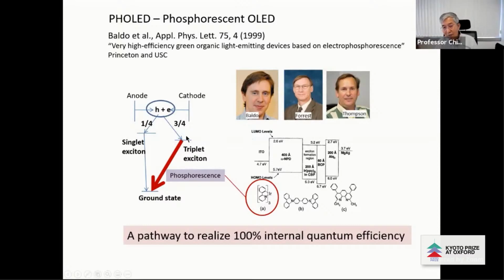At the time, we were not aware that the triplet emissions were efficient at room temperatures. Most organic materials are not. So they used iridium PPY as the emitter. The iridium is a heavy metal, which through spin-orbit coupling would allow the transitions from the triplet to the ground state with very good phosphorescent efficiencies. And with this discovery, and they had to do a lot of architecture manipulations to get the device to work properly, they provided a pathway to realize 100% internal quantum efficiencies.